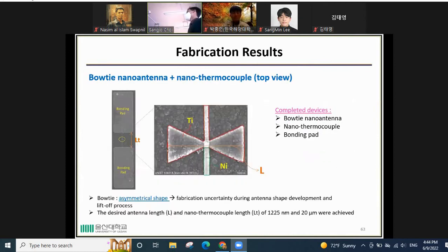And this is the completed device consisting of the bowtie nano antenna, and also nano thermocouple and bonding pad, and this is the nano thermocouple line. We can also see this kind of asymmetrical step in the bowtie nano antenna because of the fabrication uncertainty during antenna shape development and lift off process. And from this we can see that the desired antenna length and nano thermocouple length, 1225 nanometer and 20 micrometer, were achieved in our fabrication.